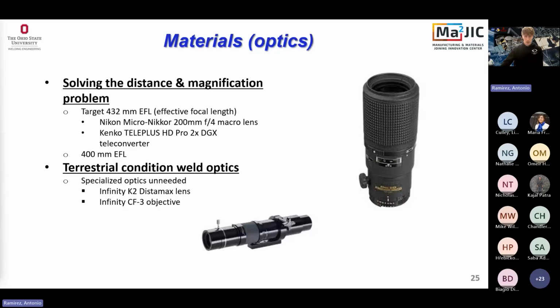It comes down to some equations that I won't explain, but basically it's very hard to get this effective focal length. But using some optics here, a Nikon Micro Nikkor 200 millimeter f/4 aperture macro lens and our 2x teleconverter, we were able to up our focal length to 400 millimeters, which is close enough to get what we need for our project. And then we also used some other optics that weren't vacuum specific to test our laser conditions, which I'll explain here in a little bit.